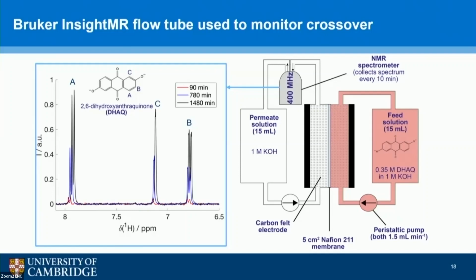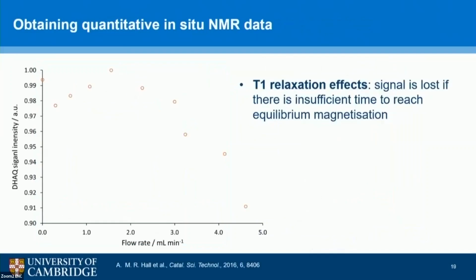So we want to use this increased intensity to measure the crossover rate. However, as we've got flow, it's slightly more complicated. So we have T1 relaxation effects to consider. As we're actually flowing the electrolyte into the magnet, if we flow too fast, we basically lose signal intensity because we're not getting back to equilibrium magnetization.